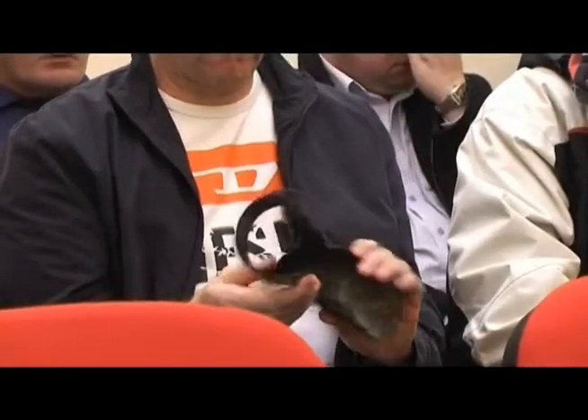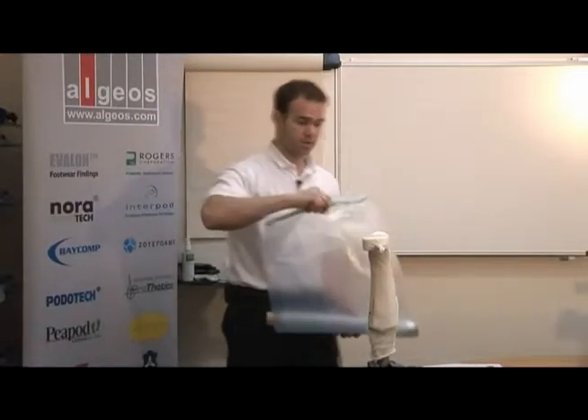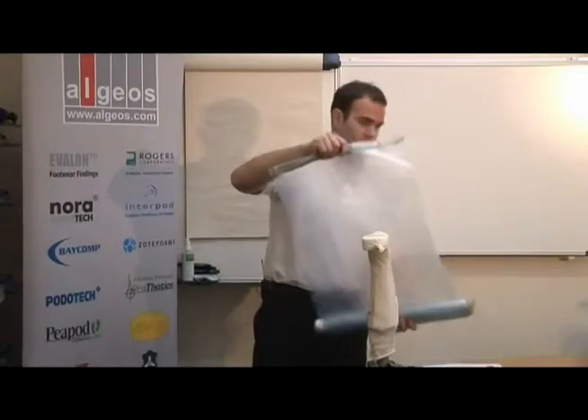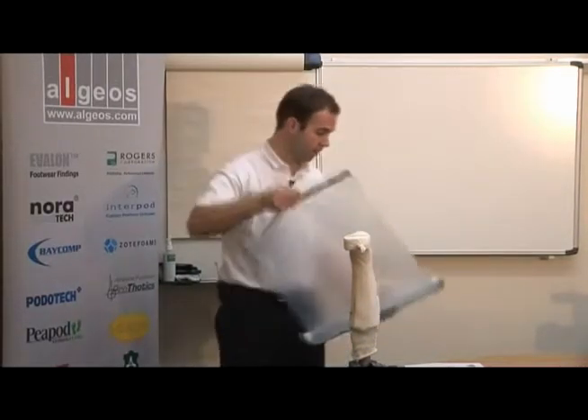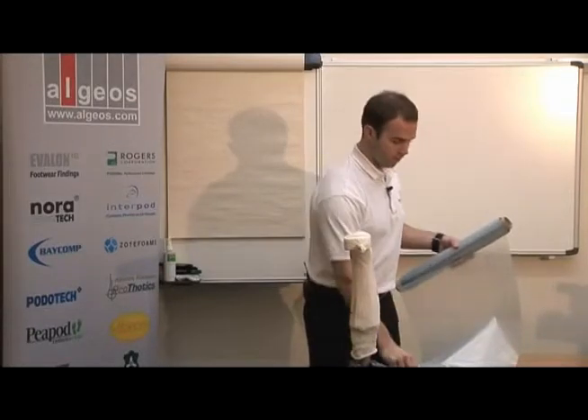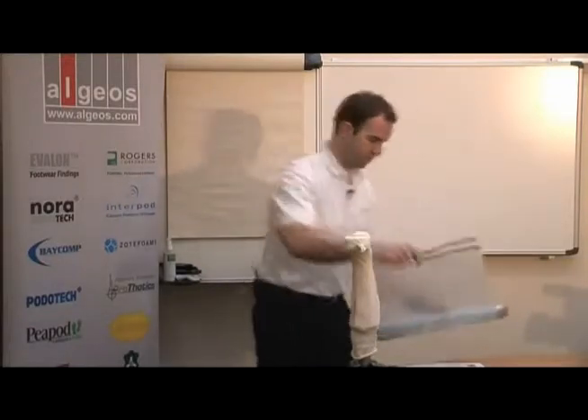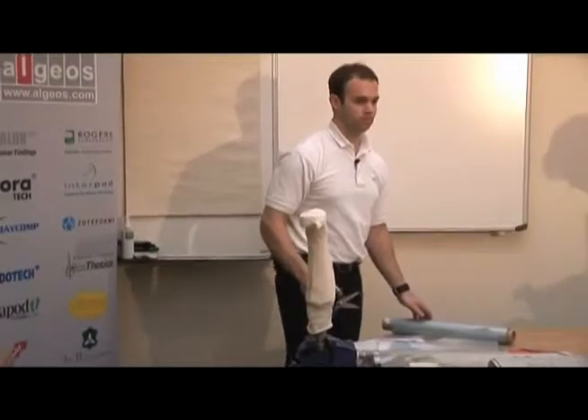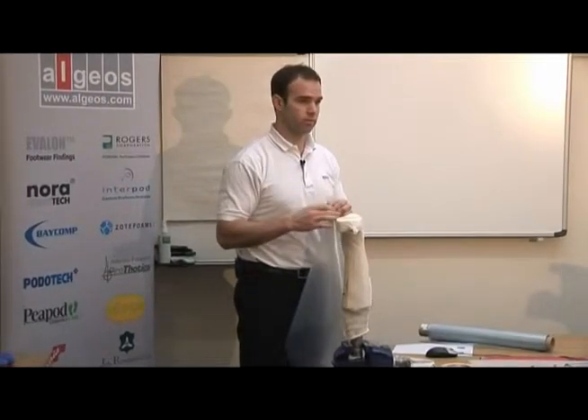To prepare for the oven, I use a nylon bag. It's sold in 10-meter rolls and it's also reusable. I've already sealed it with some sealant tape — with prepreg materials you could be using the same material. It's just a high-temp nylon vacuum bag with a working temperature of 240 degrees. We reuse it three to four times at least.